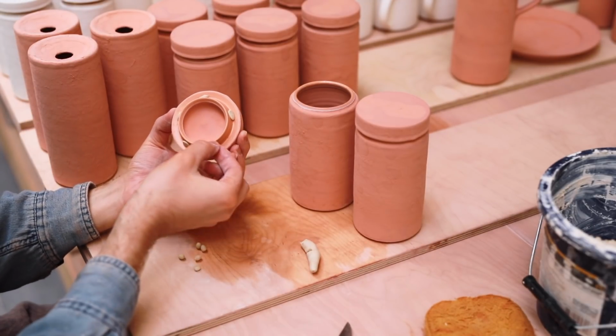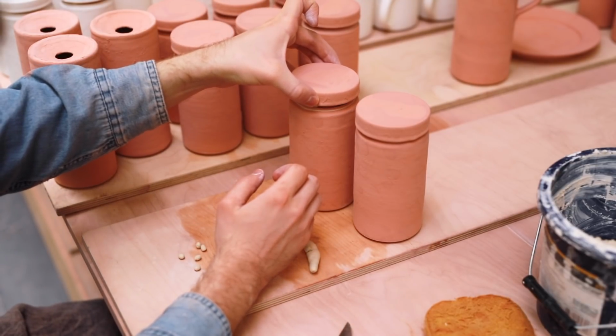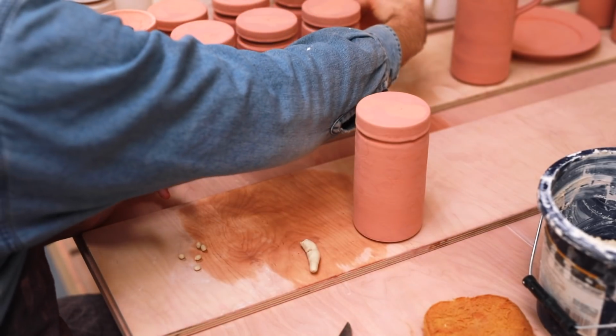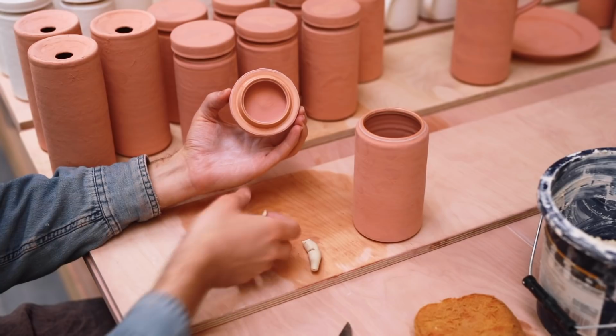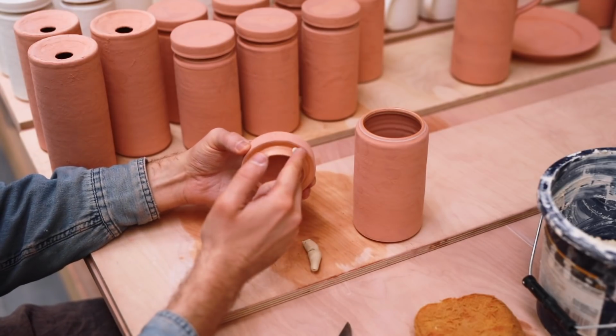They only ever touch bare clay, and they never actually come in contact with the pink glaze over top you see here. If they do, the molten glaze will fuse with the waddings, and they can be very difficult to remove. But as long as they're only touching bare clay, come the end of the firing, they generally pop off quite easily with a little bit of pressure. I then carefully place the lid on top of the jar, making sure that neither of the clay components of both the lid or the jar are touching.